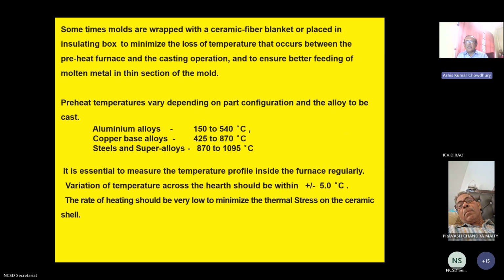Sometimes molds are wrapped with a ceramic fiber blanket, that is slow cooling, or placed in an insulating box to minimize the loss of temperature that occurs between the preheat furnace and the casting operation, to ensure better feeding of molten metal in thin sections of the mold. Preheat temperature varies depending on the part configuration and the alloy to be cast. Aluminium preheating requirement is 150 to 540 degrees. Copper base is 425 to 870. Steel and superalloy between 870 to 1095.